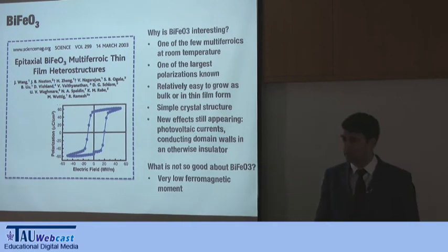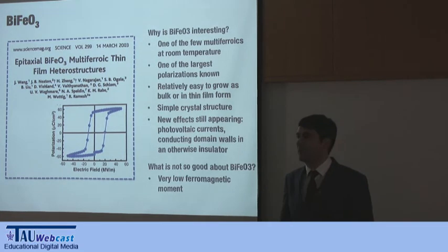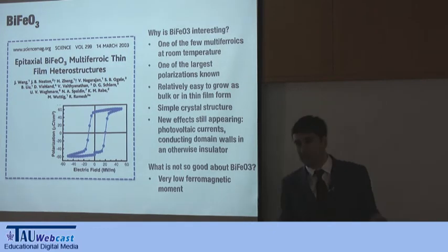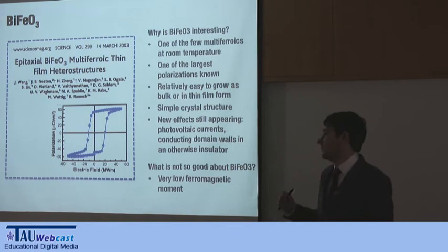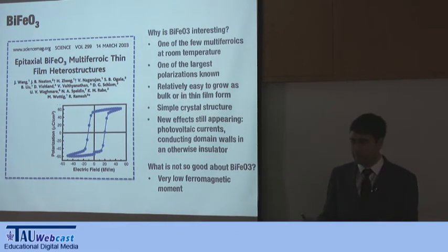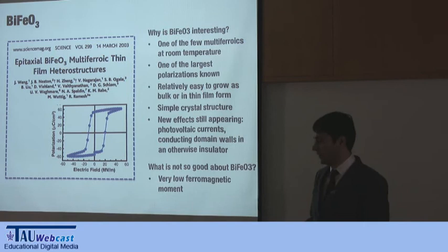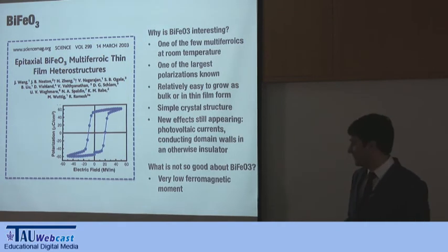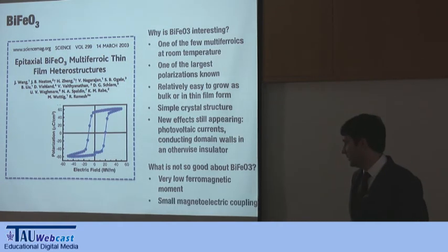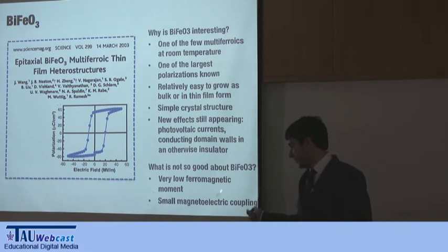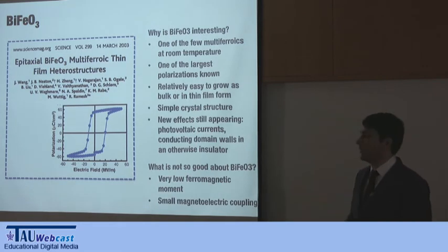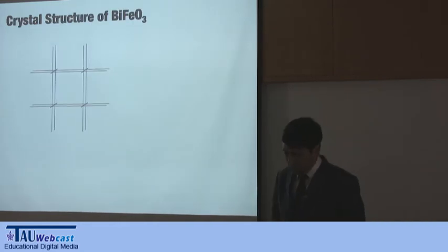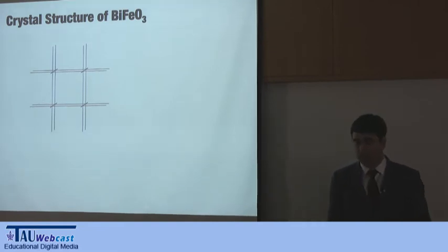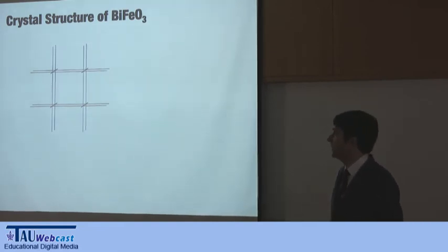What is not so good about bismuth ferrite is that the coupling between the magnetic and the electric properties is small. So you want to change the polarization with the magnetic field, but it turns out there is not a high degree of correlation between the magnetic properties and the electric properties. And also it has a very low ferromagnetic moment. So how can you improve on this? Well, one approach is to look at what bismuth ferrite is and try to improve what you have.